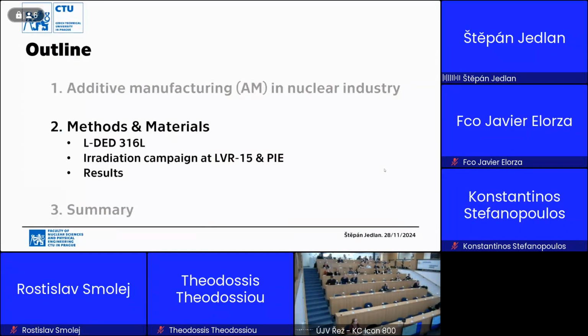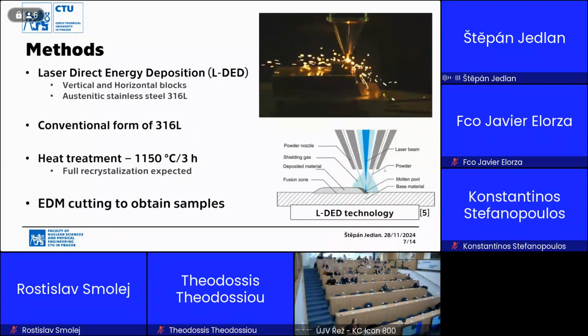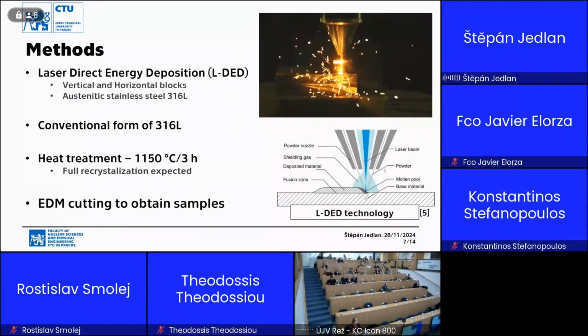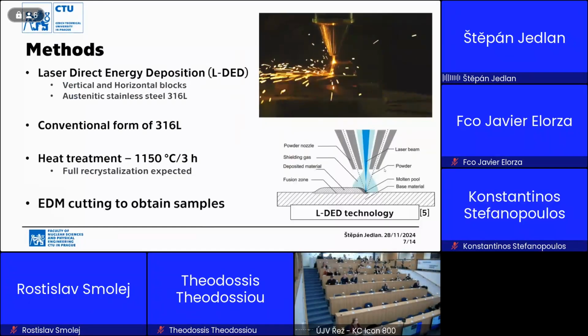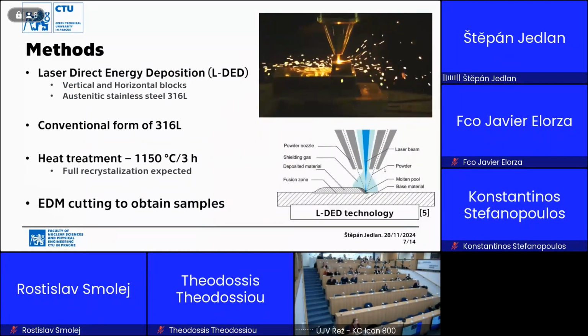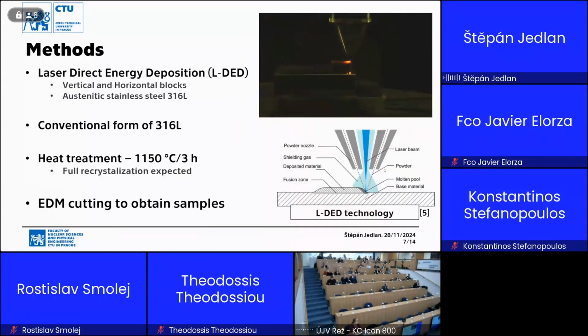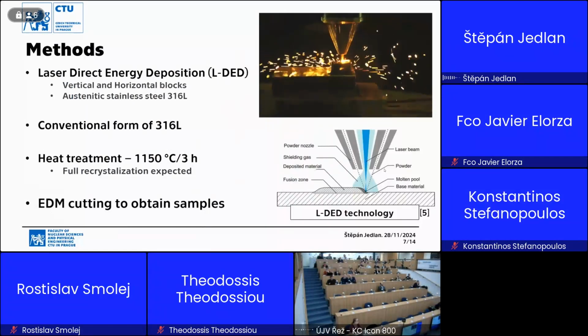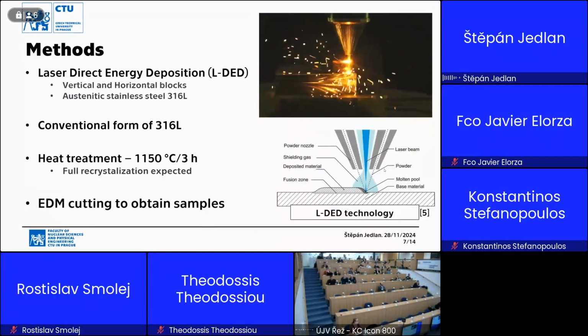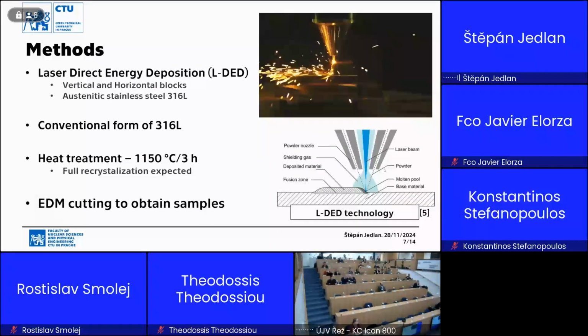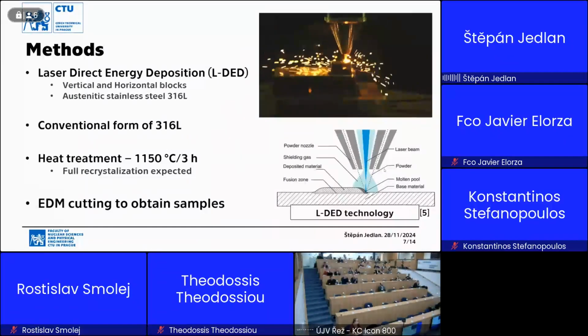And now for the experiment itself. For this experiment, we have chosen the direct energy deposition method, namely laser direct energy deposition, and we have chosen stainless steel 316L. This material was chosen because there is the largest group of research done on this material using additive manufacturing methods. We also fabricated some conventional blocks, and those conventional and 3D printed blocks were then heat treated together at 1150 degrees Celsius for 3 hours, which at least we thought would result in recrystallization, but we'll see that in a second.